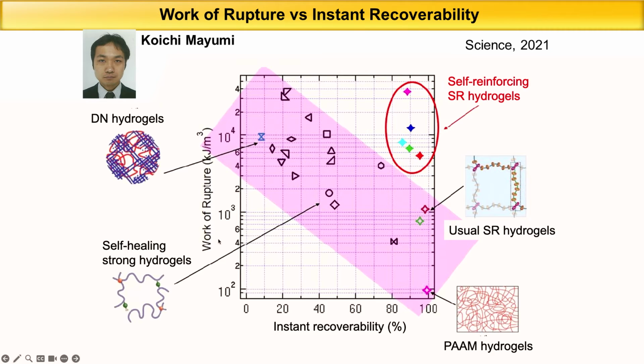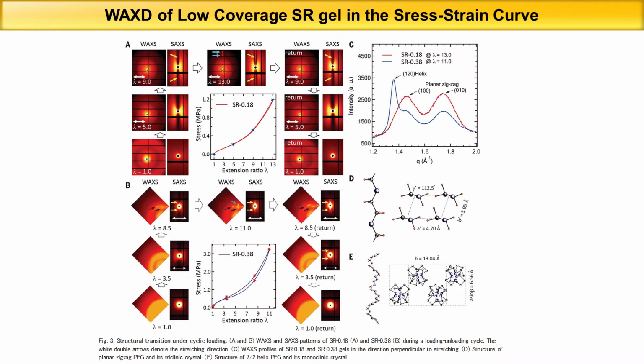And vertically, you're looking at the work of rupture, the strength of the gel. And horizontally, you're looking at the recoverability. As you can see, in the case of double network hydrogels, the strength of the gel was strong, but the recovery was poor. But in the case of this gel, the part of the crystal breaks very easily, making it harder. But if you release the force, it recovers very quickly. And that was verified with X-ray diffraction. But I won't delve into any details.